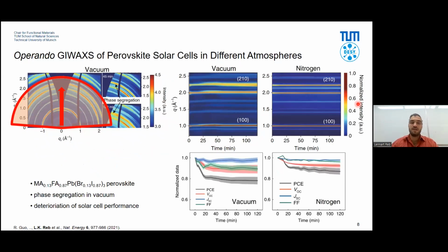So at the same time, we did maximum power point tracking with sometimes measuring the IV curves. And by doing that, we found that in vacuum, you actually have a strong decrease of power conversion efficiency within the first 20-25 minutes. Actually, in the same time where we have these changes observed, this phase segregation in GIWAXS. In nitrogen, we have no real change in the fill factor, where the fill factor here is actually the thing that is dominantly decreasing. And so by doing more analysis, so why could this happen and so on, one can reveal degradation mechanisms that act in vacuum but are somehow protected in nitrogen.